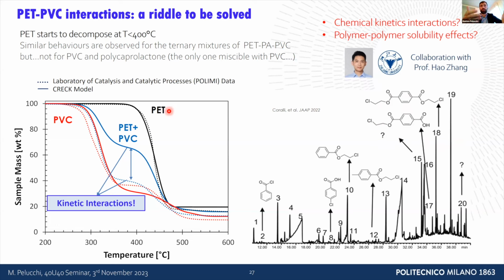Similar behaviors are observed for ternary mixtures of PET, polyamide, and PVC, but not, for example, for PVC and polycaprolactone, which is the only one that is miscible with PVC. So is it a solubility issue, or a chemical kinetics interaction issue? We're trying to solve this puzzle.